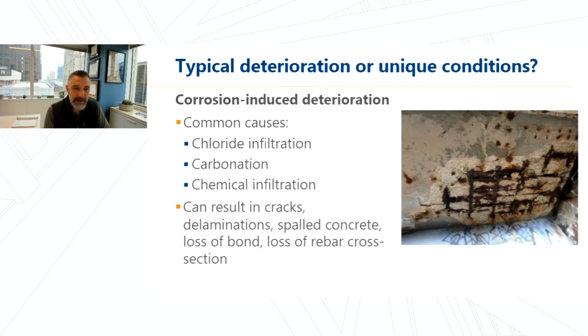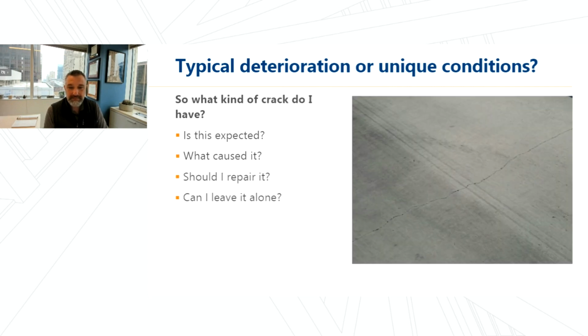So last I'm going to talk about corrosion-induced deterioration, which is when specifically we have chlorides and carbonation that work through the concrete and they eventually reach the steel and it causes corrosion. This corrosion can then result in cracks, delaminations, and eventually rebar section loss.